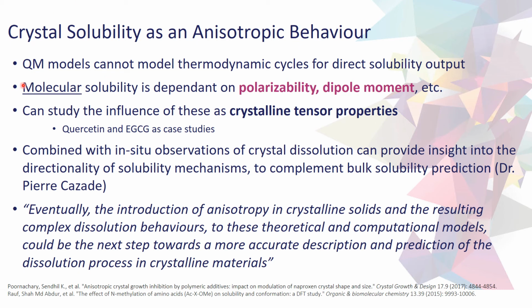But in terms of what my models can do, what DFT can do, we can try and extrapolate from what we know about molecular solubility what makes a crystal more or less soluble. So we know that in terms of molecules, like amorphous materials, the solubility is dependent on electrical properties like polarizability, dipole moment, HOMO-LUMO gaps.